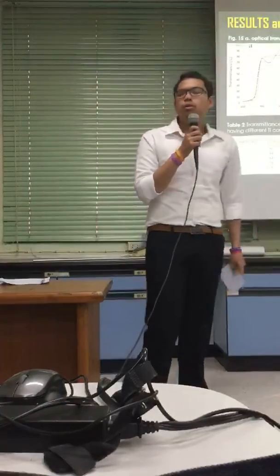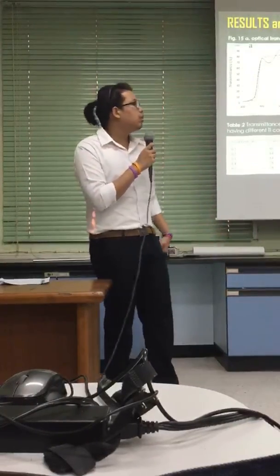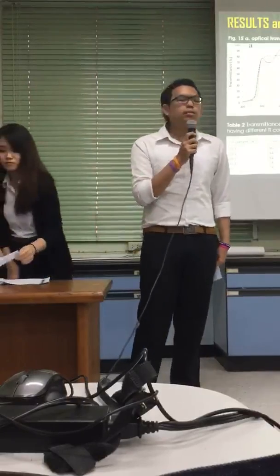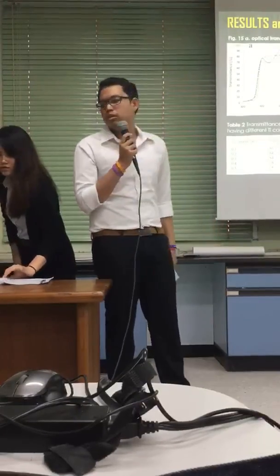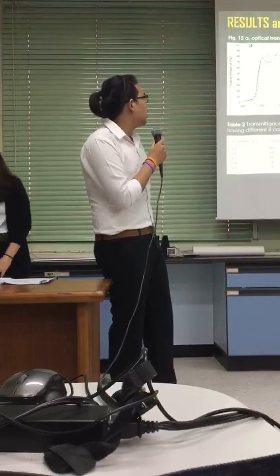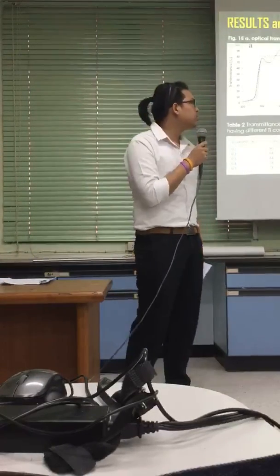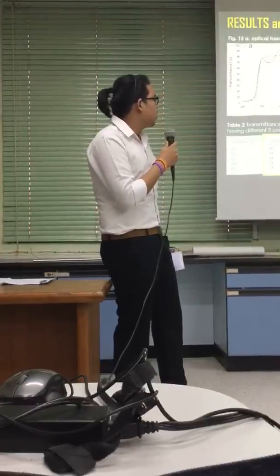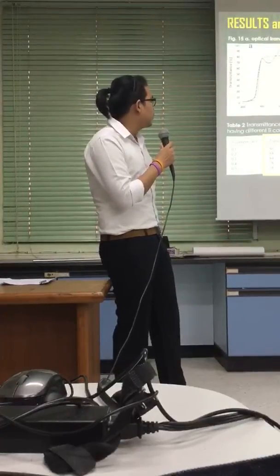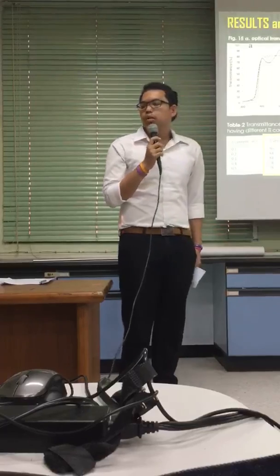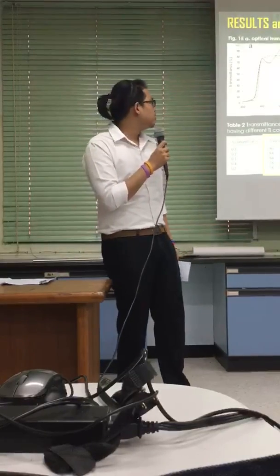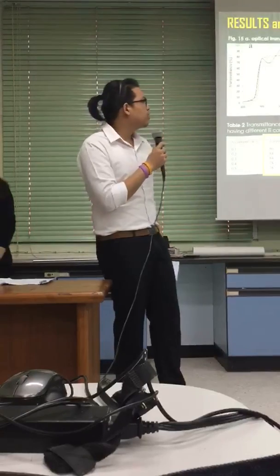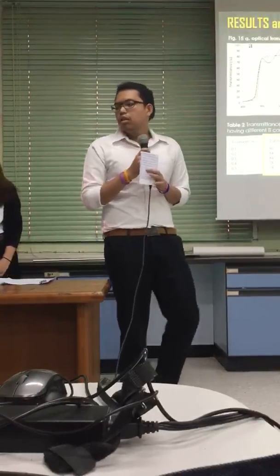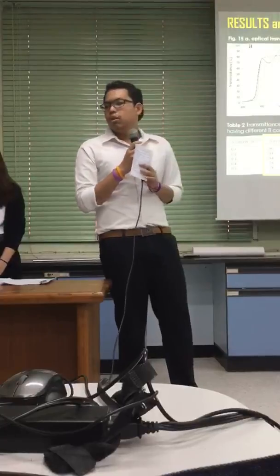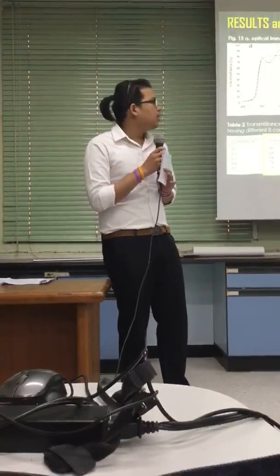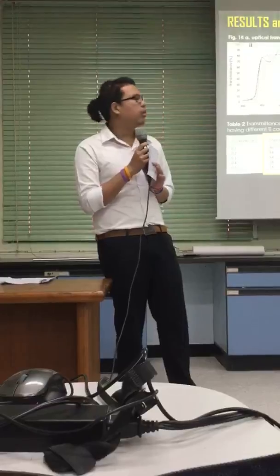Now I would like to talk about the effect of titanium content on optical properties. Optical transmittance decreased when titanium content increased, shown in Figure 15a, and Table 2 shows the calculated average transmittance value in visible range. This result can confirm that the transmittance depends on microstructures such as grain boundaries. If titanium content increases, grain boundary increases and may cause scattering effect.